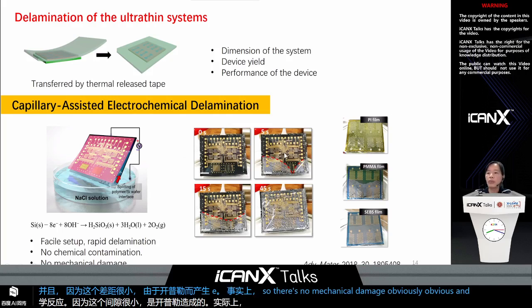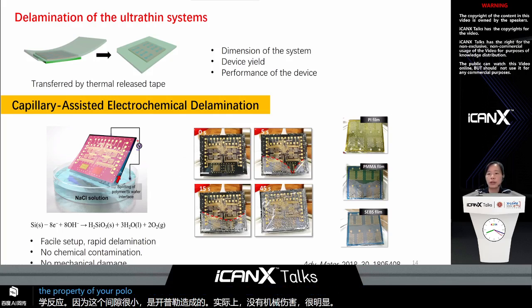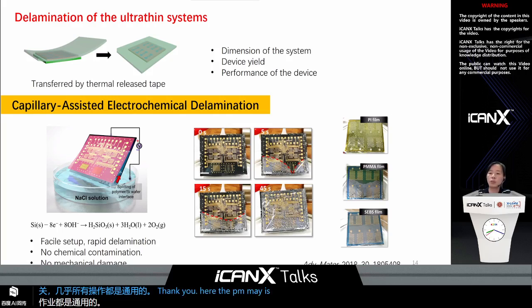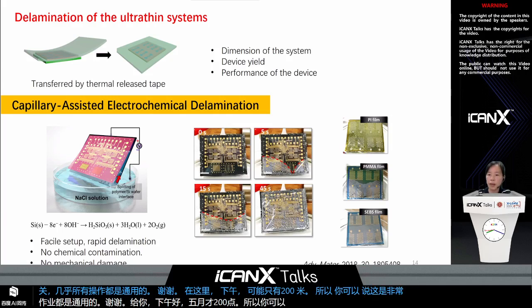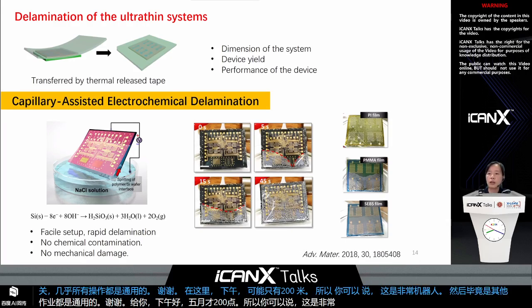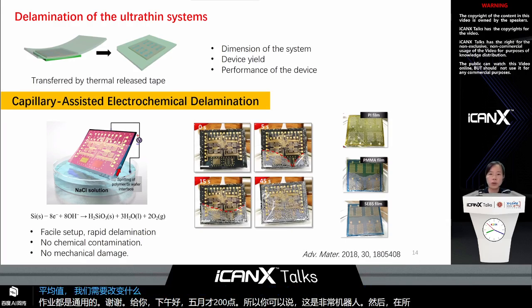And this method has nothing to do with the property of your polymer substrate, so it can work with almost all general polymer substrates. We tried it on PI film, and also PMMA, and also SEBS film. They can all work very well. And here the PMMA is only 200 nanometers. So you can see this system is very robust.